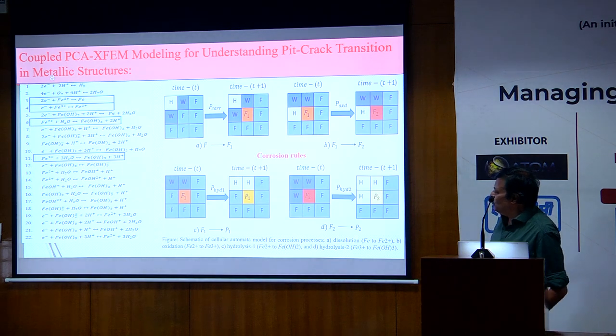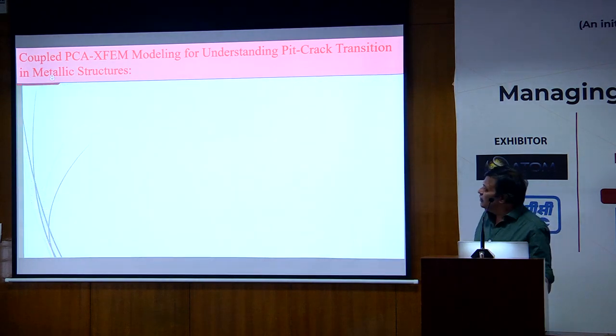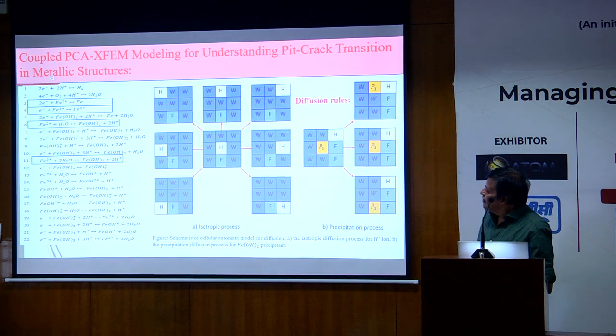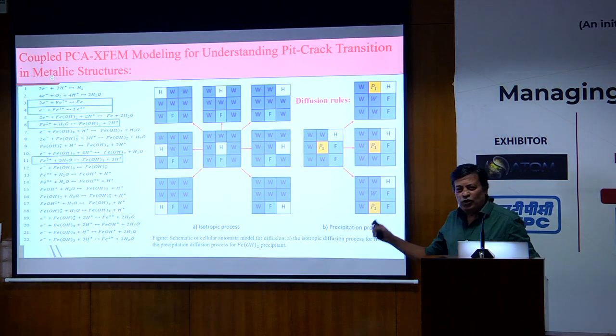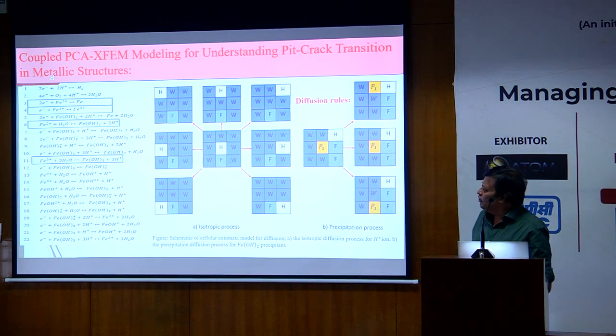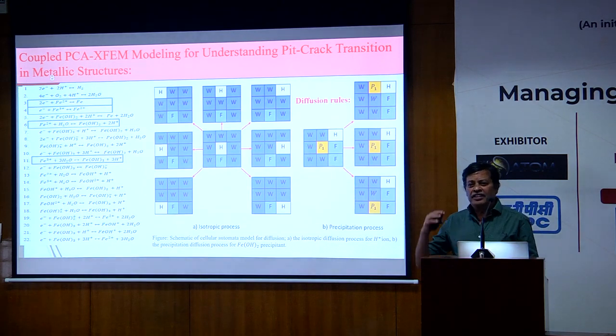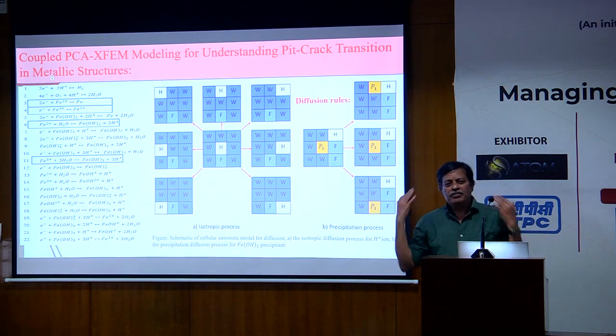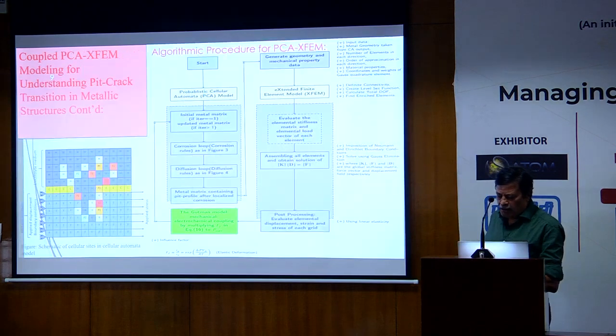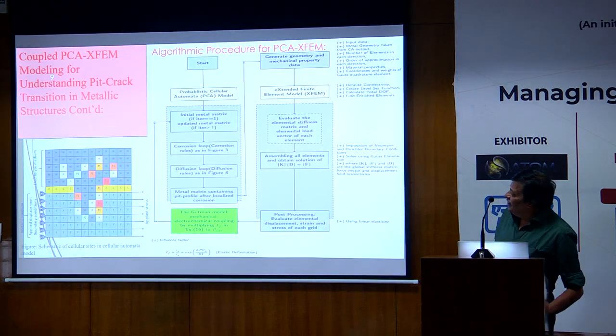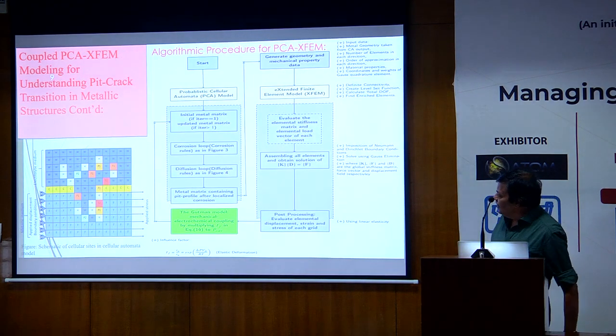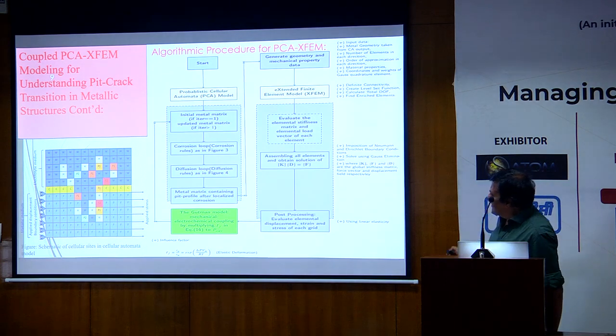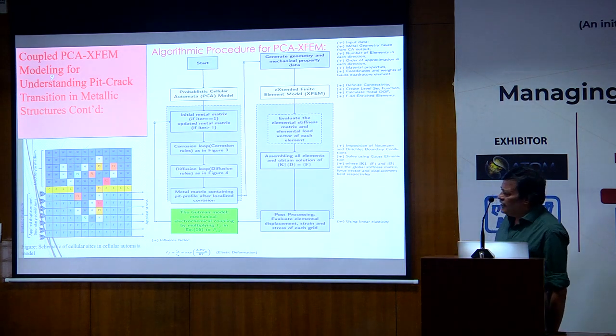And the second one is the diffusion rules. So these are the diffusion rules. I'm not going to go into them, yesterday it was all talked about. So based on this, the top layer of the electrolyte side will be modeled by this. And once we have this, again, yesterday we saw we have a Butler-Volmer-type relationship which couples the chemical model, that is the PCA model, with the XFEM model.